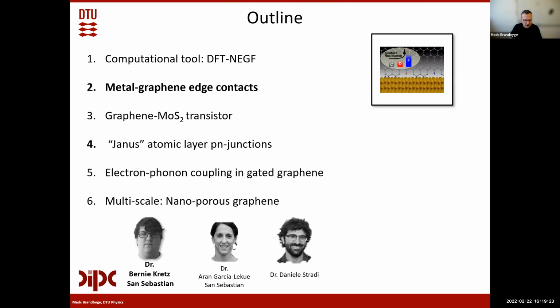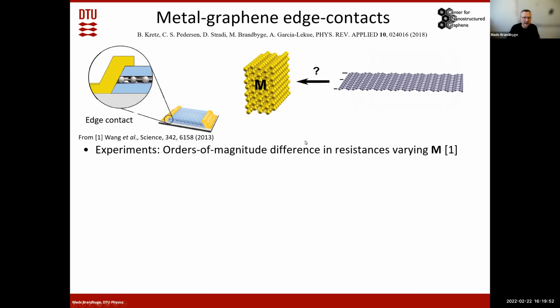Now let me skip to something which is more related to experiments, and that is the contact between metals and graphene. Because of course we need to contact the 2-dimensional materials. And one way is to use graphene as the electrode, but of course then the graphene has to be contacted. So in the first place we want to be able to control the contacts between metals and graphene. And years back it was shown how you can make 1-dimensional contacts to graphene if it's sitting inside a stack, let's say of hexagonal boron nitride, to isolate it, to encapsulate it. You can etch through this stack and then apply metals just on the side and have a 1-dimensional metal graphene contact.